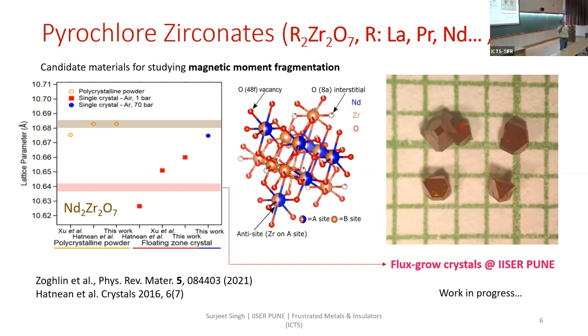And stuffing is the opposite of it, which refers to neodymium going and sitting at the zirconium sites. And both of these are really bad, terribly bad. People have experienced this in ytterbium titanate, Yb2Ti2O7. And even as of today, we don't really understand what the exact ground state of ytterbium titanate is, because a very small inadvertent stuffing or anti-stuffing can change the ground state. So our aim was to grow these crystals.